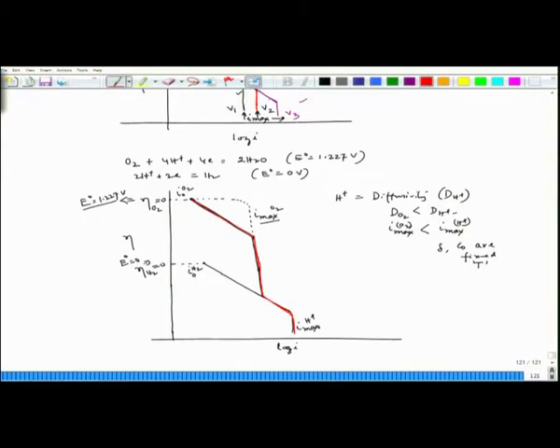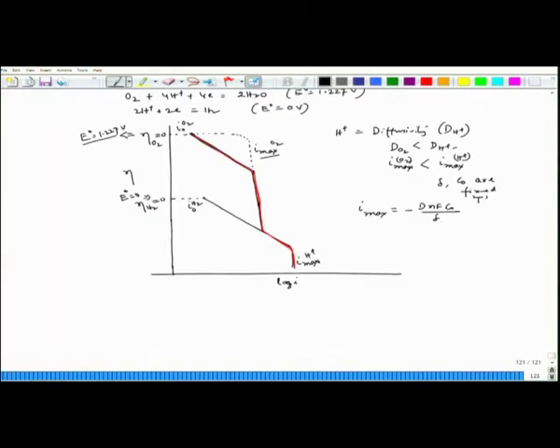If I can go up to a very high overvoltage, or a great degree of polarization on the cathodic side, this also has a relation with the diffusivity, and finally it is this equation which governs this kind of I max variation, which is minus D n F C0 by delta. So, this is about concentration polarization as well as activation polarization and how they look in combination. Now, let us get to the fundamentals of mixed potential theory.